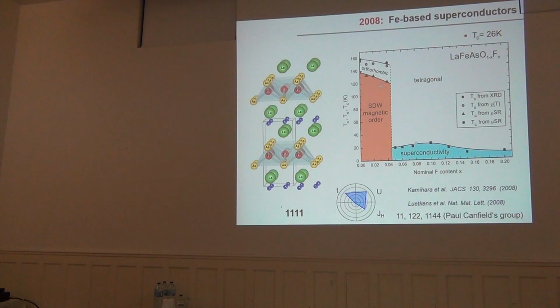Let me show you now, of course, a third class of materials, the iron-based superconductors. And I guess Paul will talk tomorrow about iron-based superconductors? Yeah, okay. So iron-based superconductors, again, let's look at the phase diagram of these systems. Temperature as a function here, I'm showing as a function of doping. Again, we go from a magnetic phase. The difference between these materials and the other two classes that I showed is that this magnetic phase is metallic, is not insulating. And then by basically doping, you go into a superconducting state, also with rather high TCs.